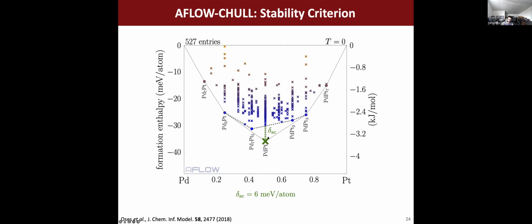And in some sense, I think this really goes to the previous question. This gives us an idea that if this distance is really large and the convex hull is fairly well converged and we've sampled a lot of different states, this tells us that the system is very stable. It's very unlikely that we're going to find a system that's going to override its precedence on the convex hull, or that, let's say, other effects like entropic effects with temperature are going to override its place on the convex hull.